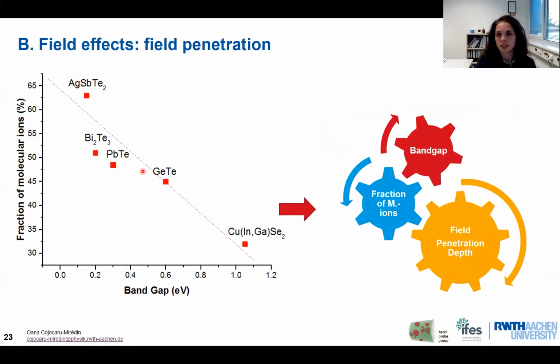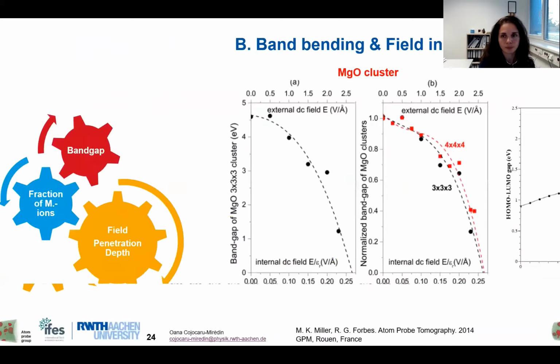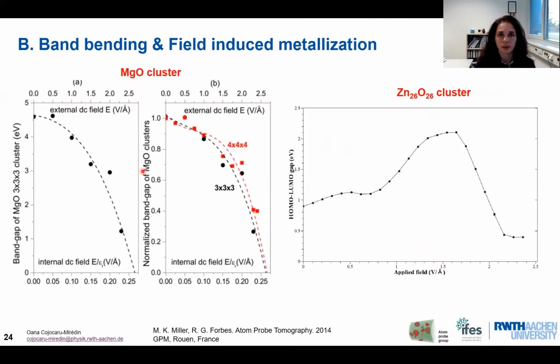So definitely this is a new research area, and in the future we need to explore the interlink between the band gap of the material, the fraction of molecular ions, and the field penetration depth. There are other important aspects like band bending and field-induced metallization. This has been shown nicely for oxide materials like MgO clusters, but also for Zn26O26 clusters. What has been shown is that the band gap of these clusters decreases as we increase the field applied on them. It decreases so much that we arrive at a point where we have no band gap. And the same has been observed for the zinc oxide, Zn26O26, clusters.